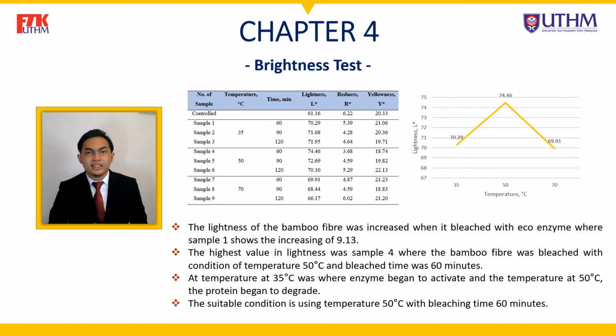For the brightness, the data has three readings, which are lightness, redness, and yellowness of the sample. The method starts with the control sample, which acts as a reference to compare the bleached fiber against. A lower lightness value indicates the sample is darker. The lightness of the bamboo fiber increased when it was bleached with ecoenzyme, while sample 1 showed an increase of 9.13 with constant temperature of 35 degrees Celsius and different bleach times. It showed that the lightness was increasing.